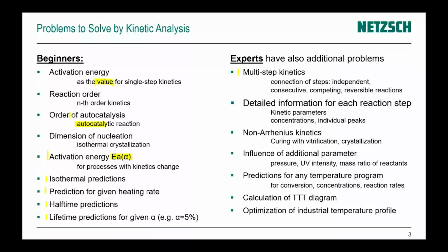You will find that not all processes are single-step processes. More than 90% of them are multi-step kinetics. And the steps inside your materials are connected differently. It could be independent steps, consecutive steps, competing steps. It could also be backward reactions, or we have reversible reactions. And you must find each step, and you must find detailed information for each step, kinetic parameters for each step, and find how the concentration of each reactant will change, including the intermediate reactant.